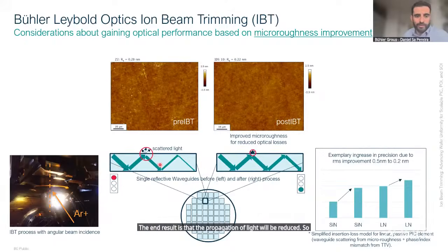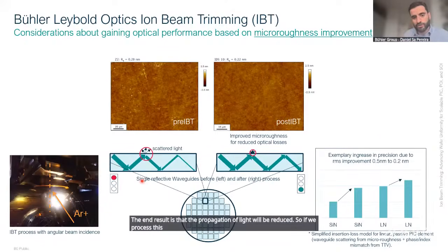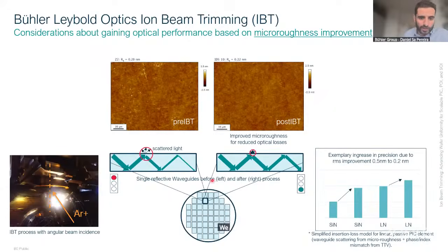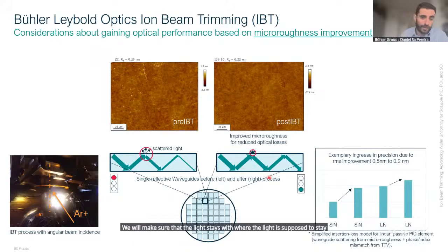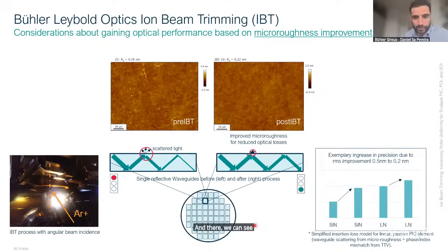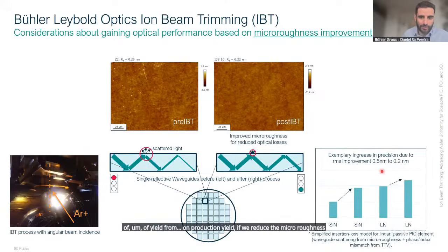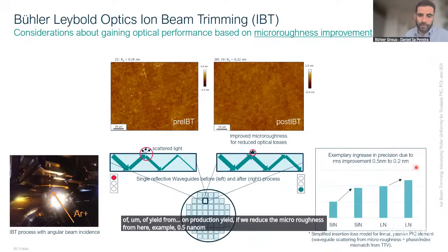So if we process this micro roughness and we reduce it even further, we will make sure that the light stays where the light is supposed to stay, meaning within the waveguide. And there we can see again that there's an improvement of production yield if we reduce the micro roughness from, for example, 0.5 nanometer to 0.2 nanometer. And this is within the scale of what IBT can do.